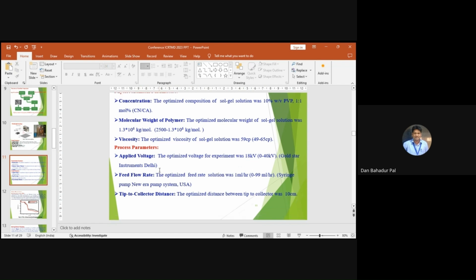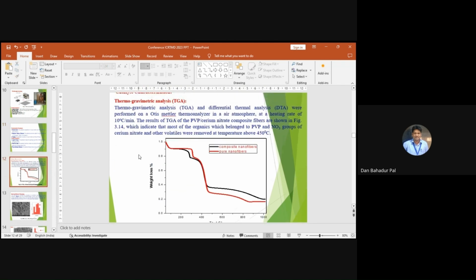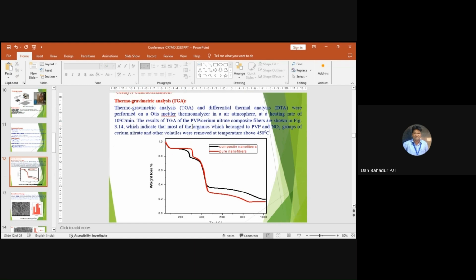So after the calcination, after the preparation, we have characterized the sample. First, we did the thermogravimetric analysis. Why are we doing this? Because through this we need the calcination temperature of the particular fibers. As per the TGA analysis, we see that after 850, in the case of pure nanofiber, there are no changes in the weight loss. It means after that there will be no loss in the weight of the nanofibers. From 100 to 200 removes the moisture content, and 200 to 400 removes the organic content.